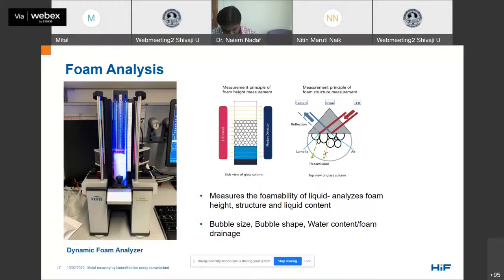Just to let you know, in the flotation process, the produced foam needs to be stable as well as unstable, depending on the stage of flotation. The stability of foam plays an important role during the bubbling stage, where unstable foam will lead to the collapsing of the foam. So if the foam is collapsed, even though the complex of rhamnolipid and metal ion is attached to the bubble, it will not be lifted up to form the foam, and it will fall back into the solution, and so we will not be able to recover this foam or metal and get the concentrated metals.